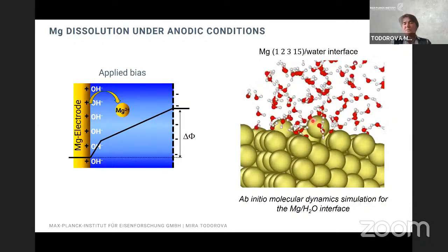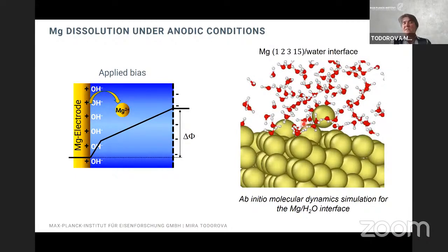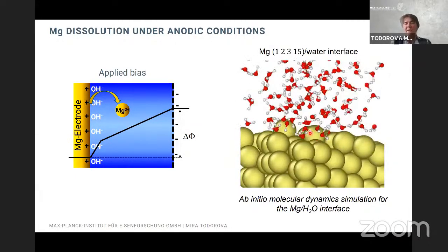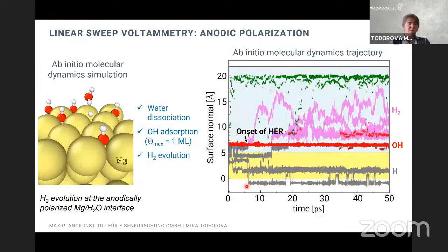What was important was that a water molecule sneaks below this magnesium atom, and then it cannot return towards the surface. We also looked at the hydrogen evolution reaction, and here we have blended out all the water molecules that are not interesting, and only left one water molecule which is participating in the reaction in order to show the mechanism. Again, you see here a plot of the trajectories, how they evolve over time. And you can see already that this diagram is much richer than what I showed you for the open circuit conditions.